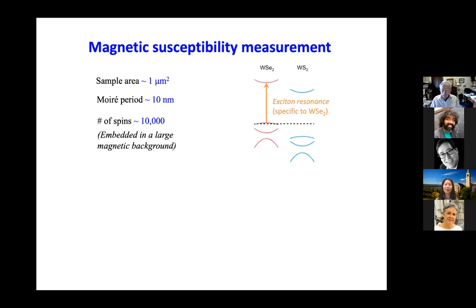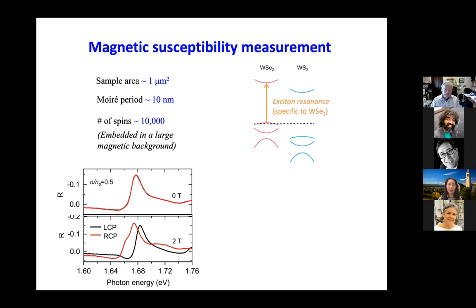So in this case, optics comes in very handy. I told you about this semiconductor, right? Because of this valley, we have an orbital magnetic moment, and the light couples to it following valley-dependent optical selection rules. So if you come in with left circular polarized light, it will couple only to one valley. And if you come in with the other handedness of light, it will couple to the other valley. So the helicity of the photon is a very good probe of the valley pseudospin. Therefore, we can use this technique to look at the difference between the K and negative K valley population, so to speak. So that's exactly what we did.